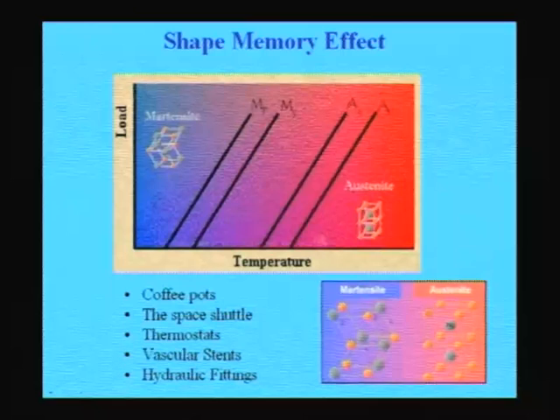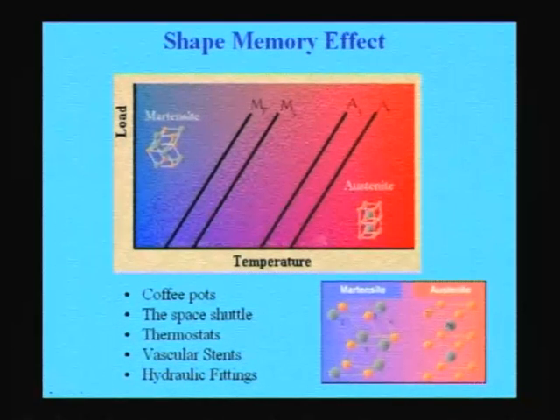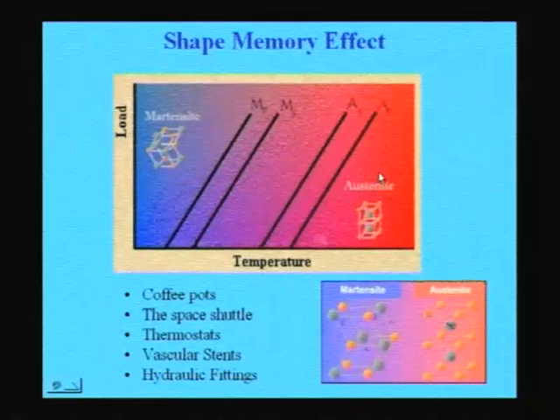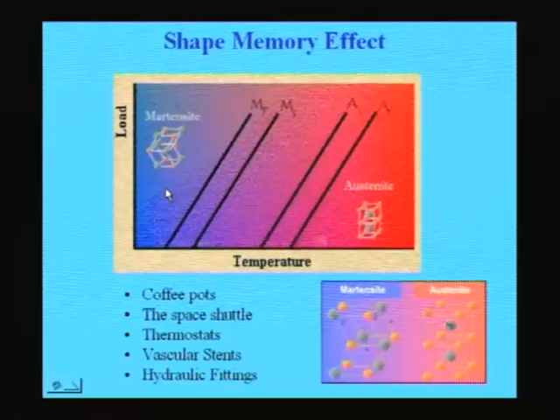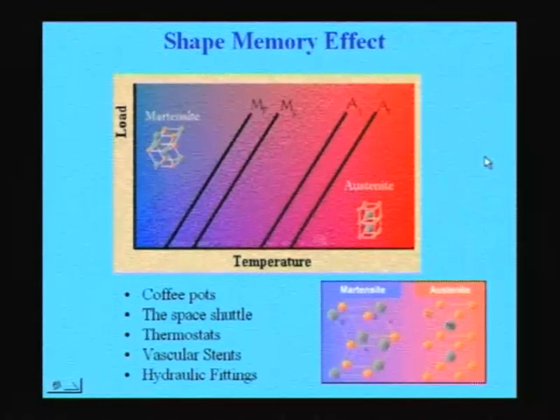So from that you can see when you load a material, depending on the type of structure, the transformation temperature changes. Here the transformation temperature increases with increasing load. If you look at the high temperature austenite, it is shown in red color because the temperature is high. This austenite, if you bring it back to the martensite by cooling it down, and this martensite is deformed and then heated back, you get back the original shape of the original austenite, and retain whatever shape you had in the original condition. In fact, I had a few video clippings I wanted to bring, but somehow they were not working on this PowerPoint. Maybe some other time I will show you those clippings.